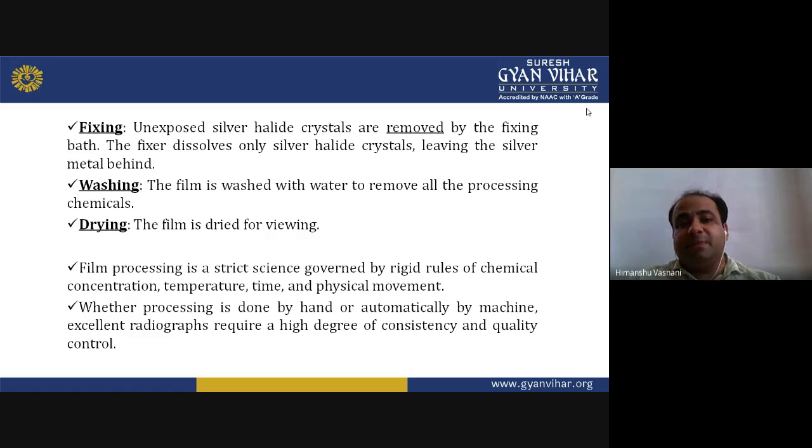Then fixing. Unexposed silver halide crystals are removed by the fixing bath. The fixer dissolves only silver halide crystals, leaving the silver metal behind. Then you go with the washing process. The film is washed with water to remove all the processing chemicals. And last, drying. In the drying process, the film is dried for viewing.